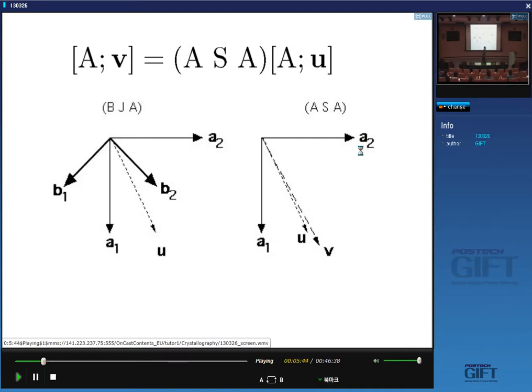Now, the reason why we need to use deformation matrices, which have the distortions eta 1, eta 2, eta 3, instead of a strain tensor, is that strain tensors are only valid for very small deformations. If you look at your strain tensor with epsilon 1,1, epsilon 1,2, and so on, those are very small quantities, and therefore it's basically an approximation to deformation. Those approximations are not important when your strains are very small.